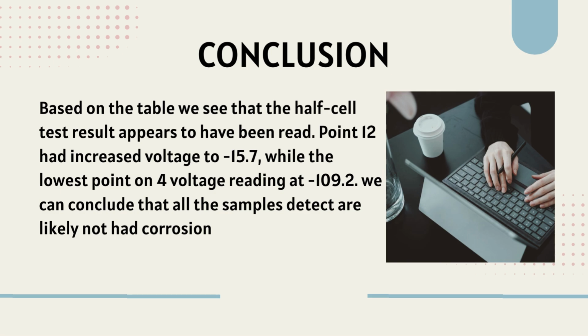Point 12 had the highest voltage at negative 15.7, while the lowest point had a voltage reading of negative 109.2, so we can conclude that all the samples detected are likely not to be corroded.